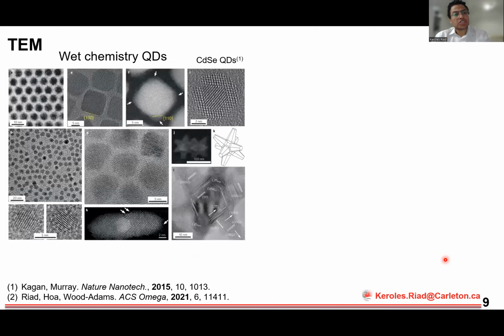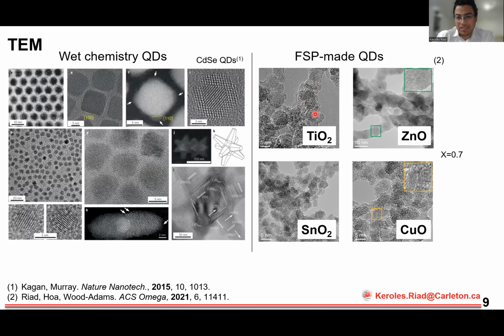Now, going back to the literature, with wet chemistry quantum dots, you have those beautiful TEM pictures of single crystals that are very well defined and very easy to measure the crystal size. Now, my quantum dots might look like this, and it's still relatively easy to see the crystals here, but as is typical with all flame-made particles, they're very agglomerated, which begs the question: are FSP quantum dots as good as the ones made with wet chemistry?